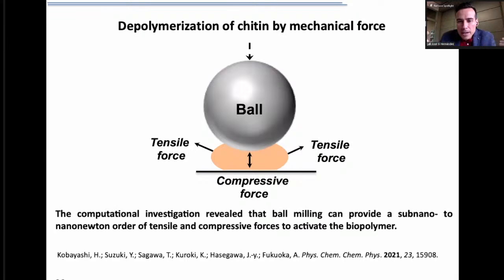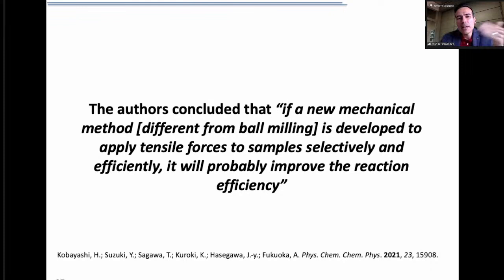This is important because when you do ball milling, especially by using mixer mills that we saw at the beginning, we consider most of the time the strength of the collision, the compressive forces, and sometimes the shearing forces, while those tensile forces are overlooked. However, they demonstrated that it is possible to also achieve tensile forces, which can bias chemical reactions and facilitate the cleavage of certain bonds. And the authors, after experimental and computational studies, concluded that if a mechanochemical or mechanical method, different from ball milling, is developed, which can apply tensile forces selectively, that could improve how the reaction works.